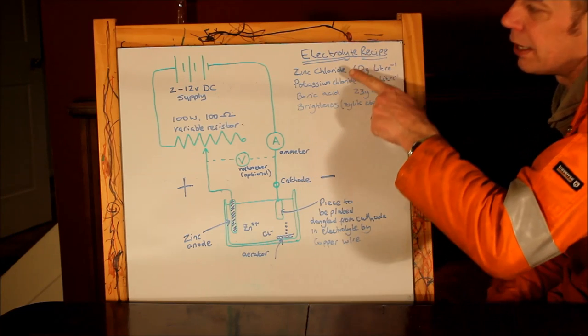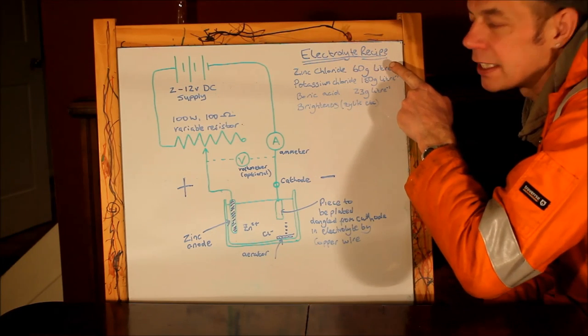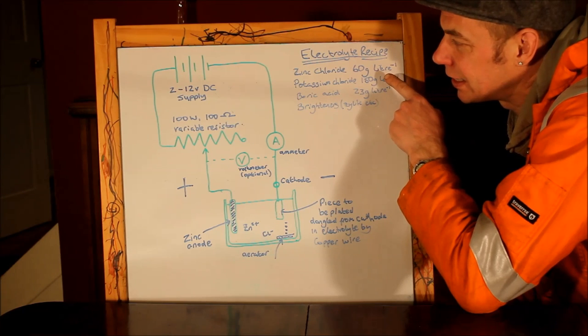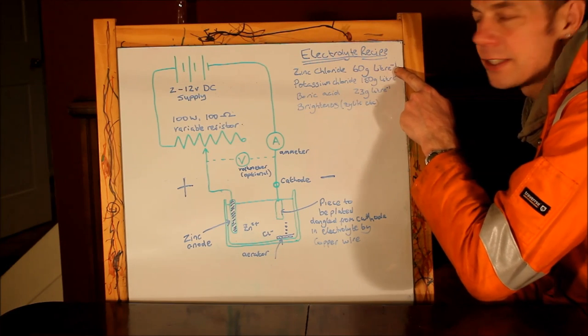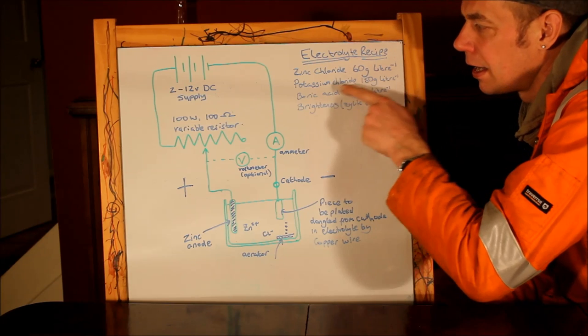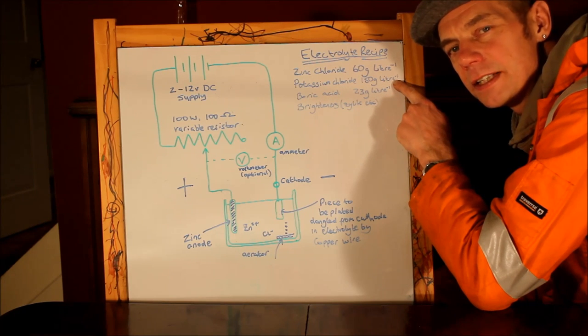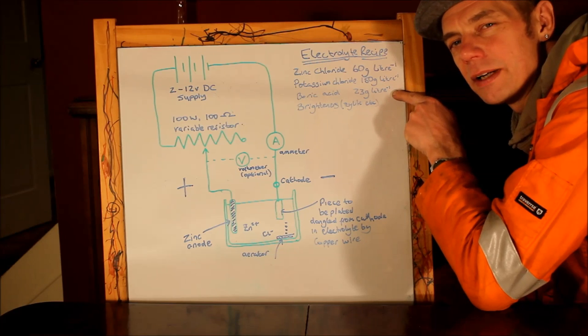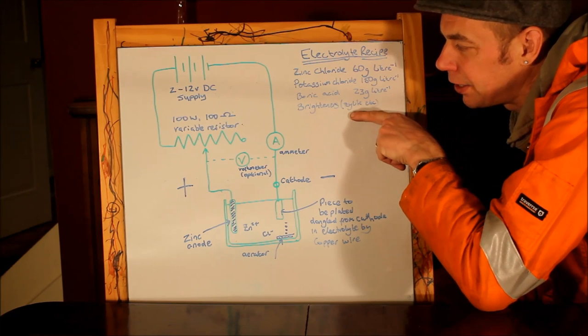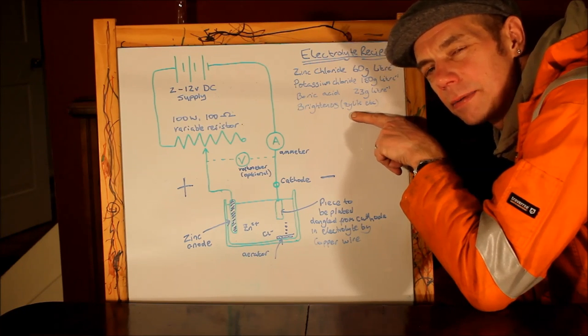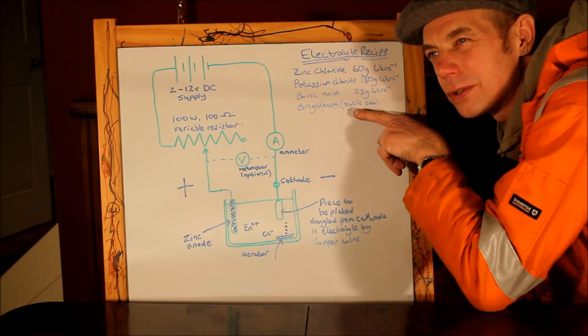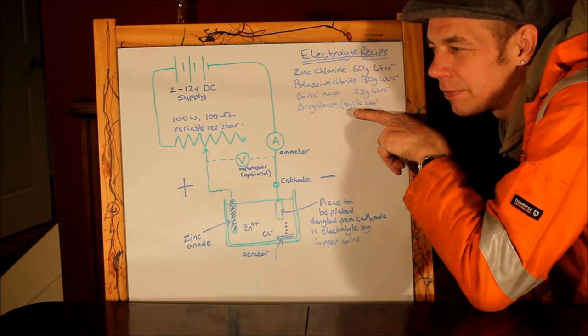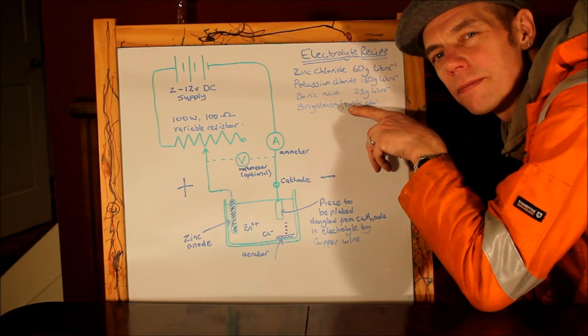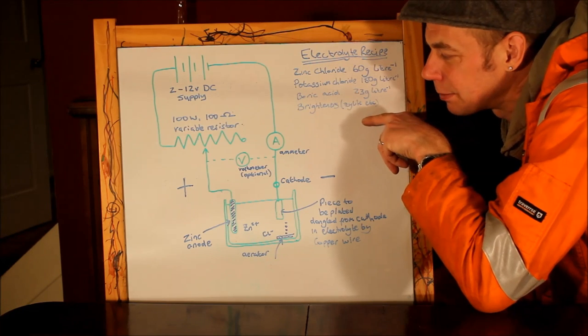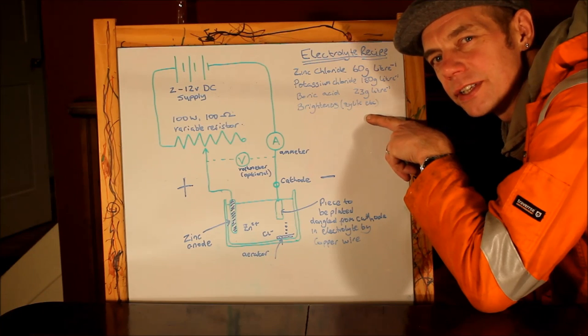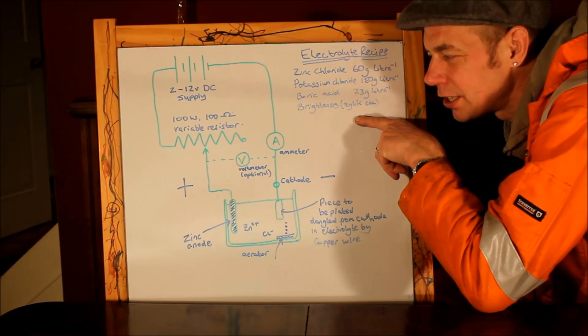The electrolyte we're going to be using is based on zinc chloride, so it's a slightly acidic solution of zinc chloride, about 60 grams per litre. Then there's potassium chloride, about 150 grams per litre, and boric acid, 23 grams per litre. It's a very good idea to add brighteners, the proprietary brighteners. One is called xylite, and there's various ones available from the plating chemicals suppliers, but add those according to the manufacturer's instructions, and that'll give you a much brighter finish.